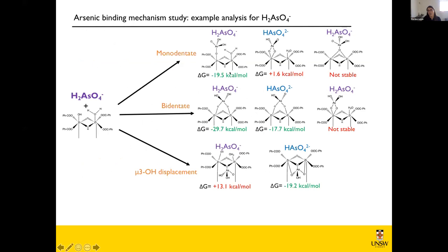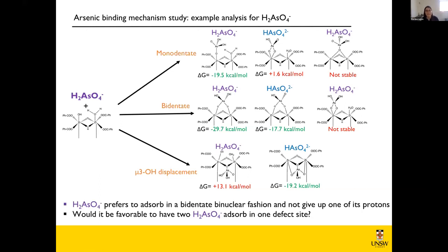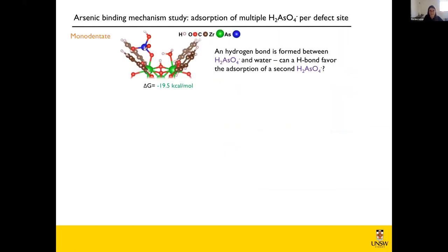You can see that overall, the monodentate, bidentate, and μ3-OH displacement modes are probably the most favorable modes we can see. But in general, the bidentate is definitely the most favorable, by about 10 kcal per mole. But the questions we had, in addition to this type of analysis, came up after we looked at the monodentate mode a little bit closer. As you can see here, there is a hydrogen bond being formed between the arsenic species and the water molecule.